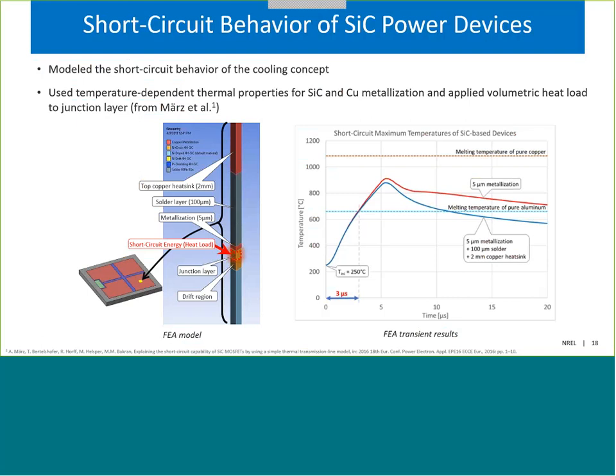And so we've also done some work to model the short circuit behavior of the cooling concept. It's well known that the short circuit withstand time of silicon carbide MOSFETs is lower than that of silicon IGBTs. And so what we're trying to do here is to see if the current cooling concept has any effect in delaying the temperature rise during a short circuit fault condition.